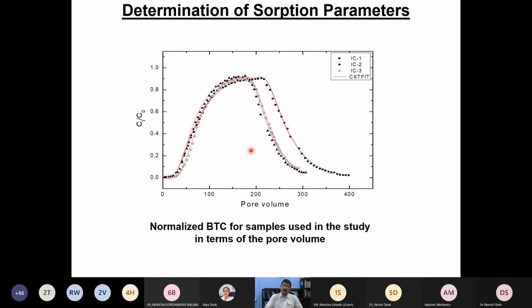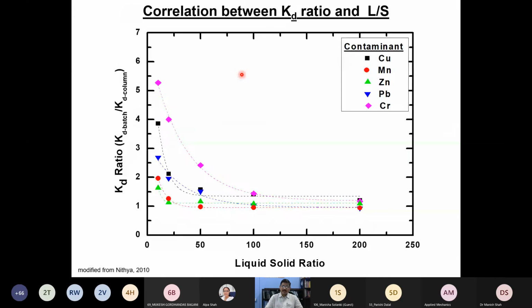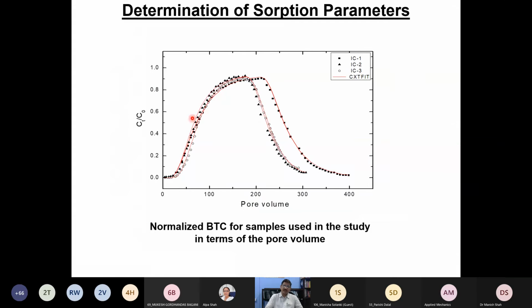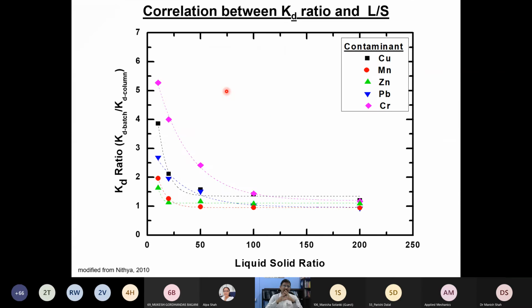Because anyway, the desorption curve I don't really need at all, but I am more interested in the sorption curve. So by using this data, we can back calculate by fitting this theoretical curve, and I can get the KD parameter. We have 3 KD parameters. One is the KD parameter from the batch test, which is very, very simple. We also got the KD parameter from the centrifuge. We correlated the KD parameter from the 1G test in the column flow through experiment versus a centrifuge. We noticed that these two are matching very well.